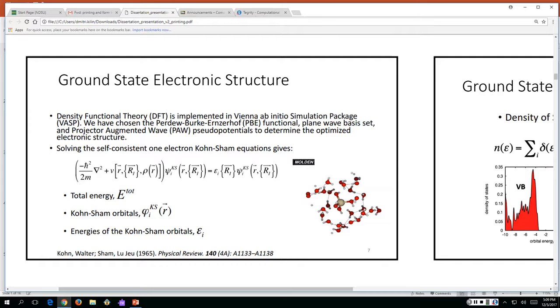within the system. And so this unoccupied orbital will produce dynamics similar to that of just the vacancy closed shell system, as they both have an unoccupied state within the band gap. Now, with the addition of multiple K-point calculations, the major difference occurs in the shape of the bottom of the conduction band. And so there are extra states that are added in at the bottom of the conduction band that may lead to different rates calculated out.